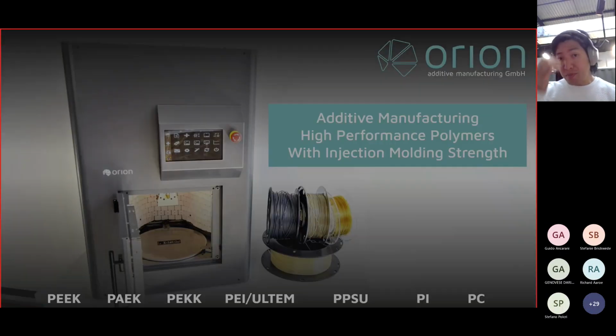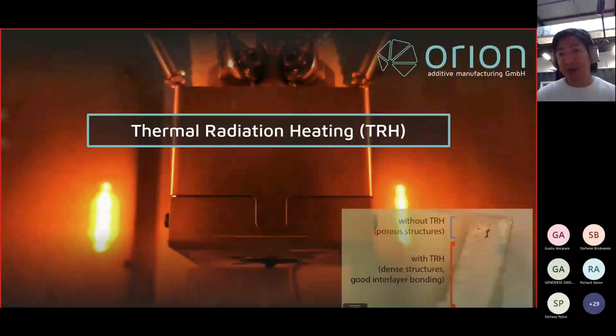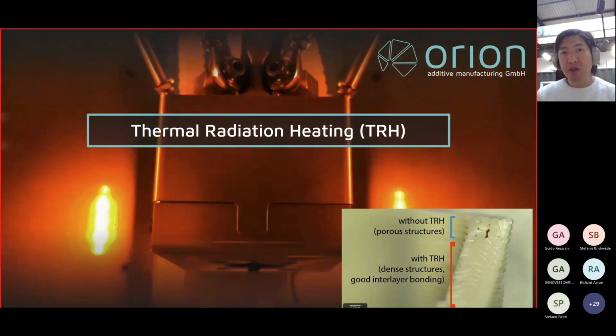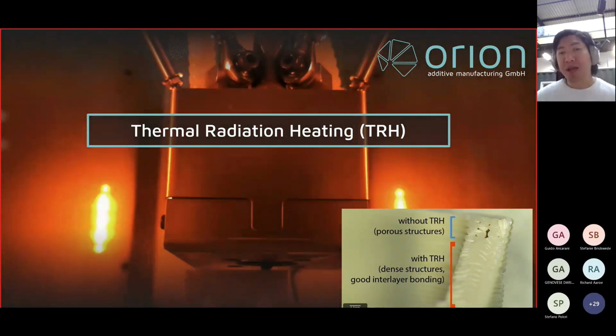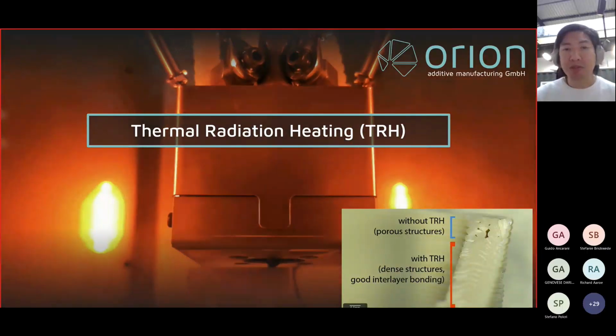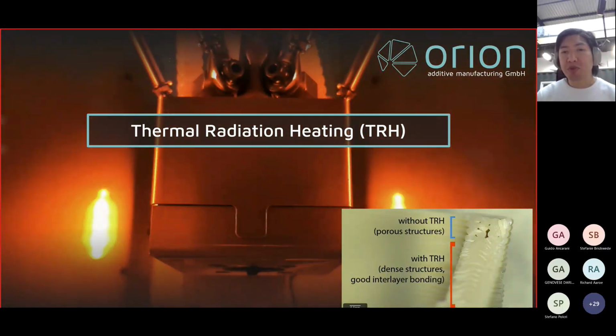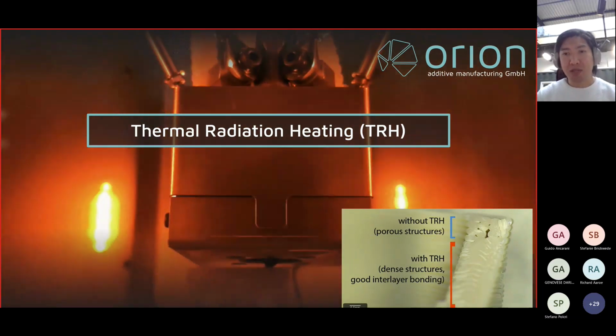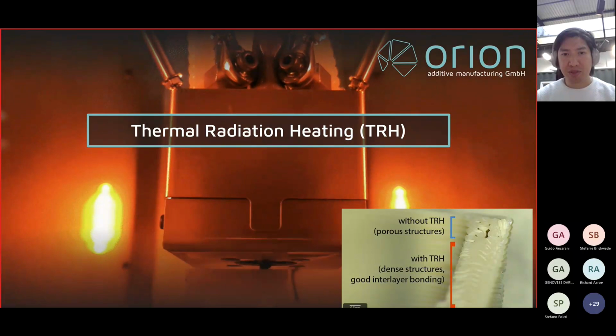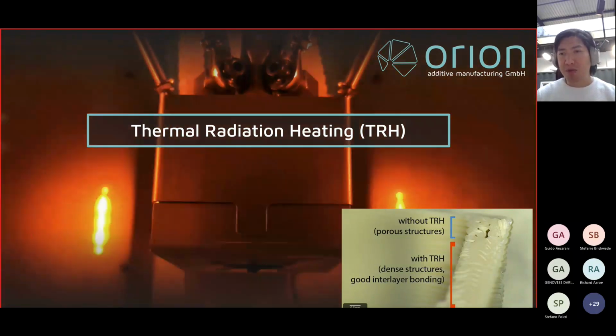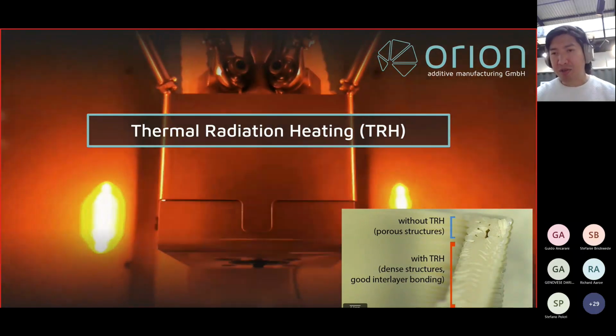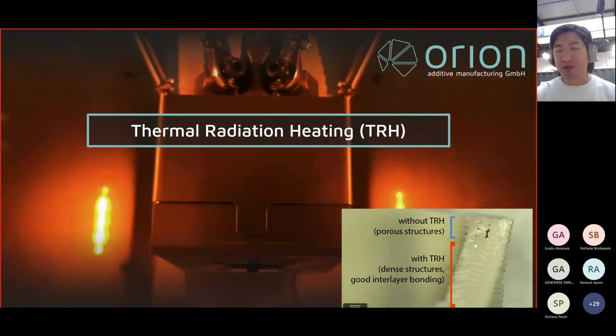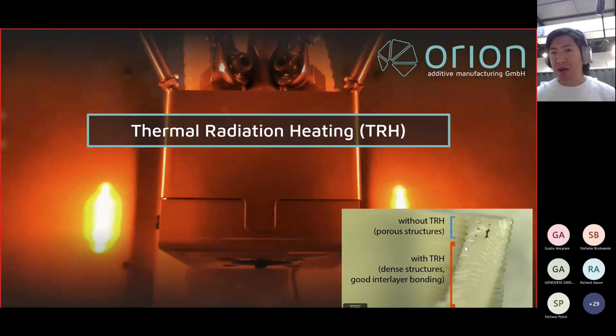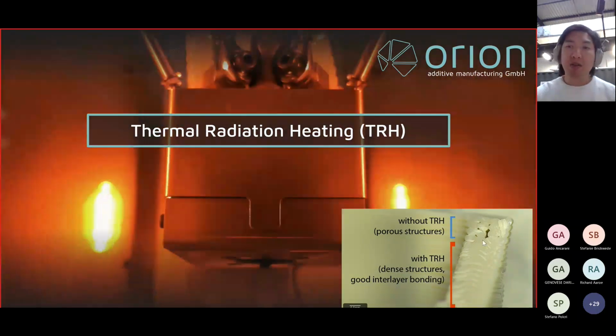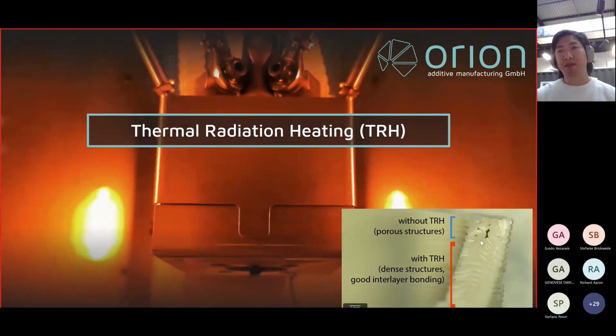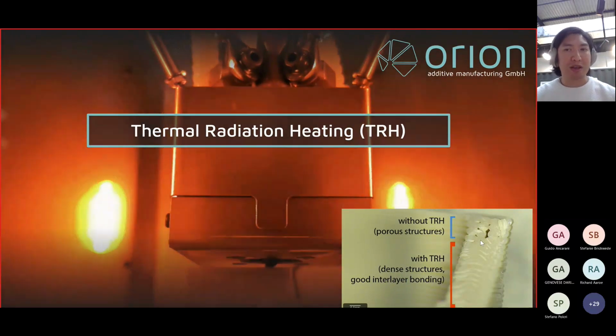So what we've done is we created a proprietary process that we developed on our own over the last 4 years, which uses thermal radiation to apply energy towards the material during the printing process. And when we do this, we're able to fuse all the layers together, and we're able to get a nice consolidated structure that's homogeneous and fully dense on the inside. So you can see on the bottom right here, in the bottom section of this image, how the internal structure looks when we use thermal radiation heating, and what happens when we turn it off. And this is when you start to see these voids show up again, and it lowers the density and also lowers the bonding of these layers.